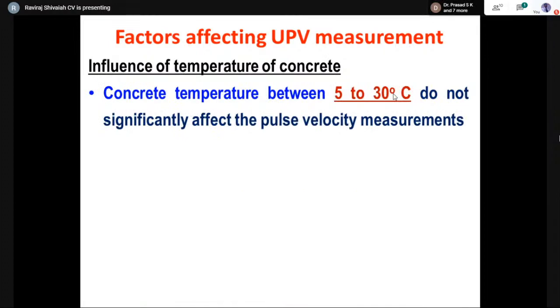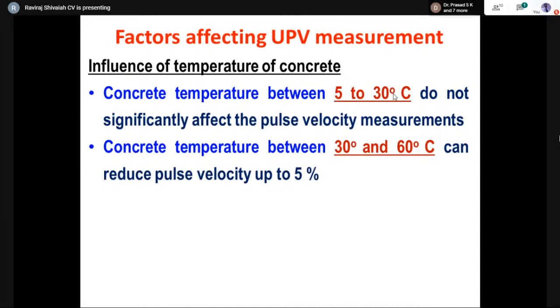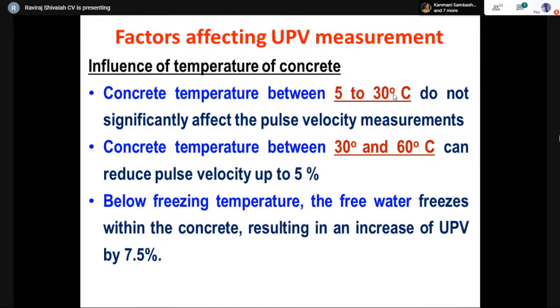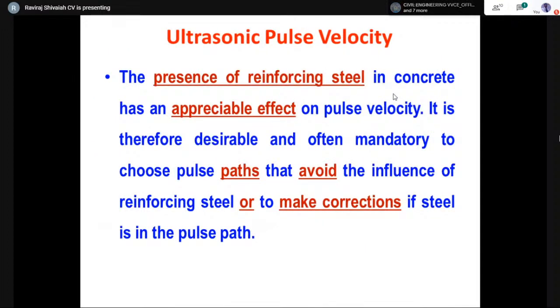Regarding the temperature, generally 5 to 30 degrees is perfect. If you're operating between 30 and 60 degrees, there could be some influence on the pulse. That means the velocity can reduce here, and especially when testing at temperatures below the freezing point. Please understand, the water can freeze inside the pores, and that can result in an increase in UPV of 7.5%. So all these things will be noted by the expert when he does the testing.